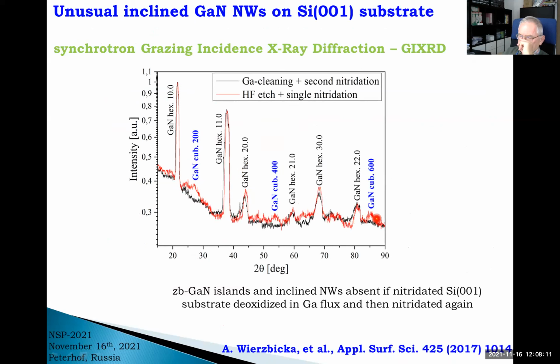We have checked this. The zinc blende inserts can be visible by X-ray diffraction, of course, not in a classical version, but using synchrotron in a special grazing incidence just to get insight into the surface only. And you see that if we use only HF and nitridation, so we suppose that these islands of oxide are still left and we grow on top of them, we have these cubic gallium nitride reflections. But if the same substrate after HF and nitridation is cleaned with gallium and then nitridized again, these peaks disappear. So this means that these residual oxide islands really cause crystallization of these gallium polar nanowires.